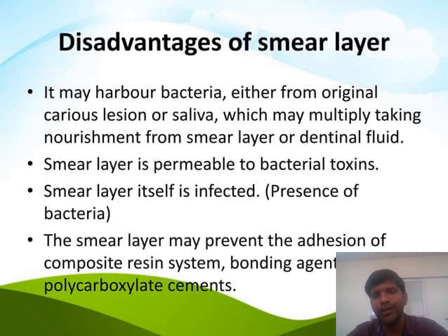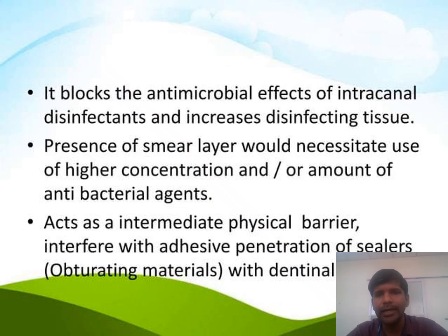The smear layer may prevent the adhesion of composite resin system, bonding agent, and zinc polycarboxylate cements. It blocks the antimicrobial effects of intracanal disinfectants and increases the disinfecting time. And the presence of smear layer would necessitate use of higher concentration or amount of antibacterial agents. It acts as an intermediate physical barrier that interferes with the adhesive penetration of the sealers, that is the obturating materials, with the dentinal walls.